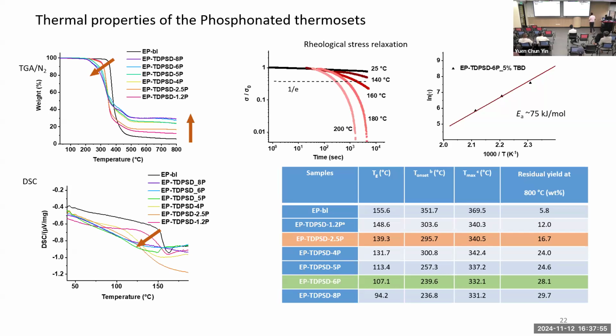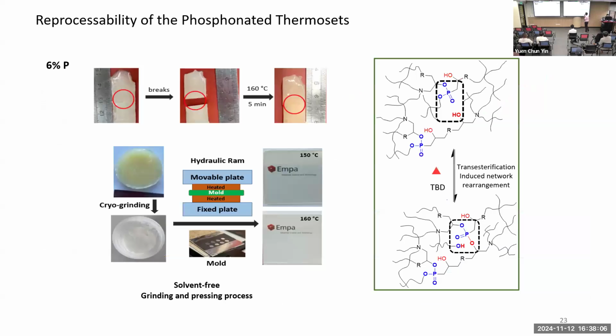Okay. So take home message. Higher the phosphorus, easy to recycle, but also lower is the glass transition temperature, and higher is the char content of the material, I would say. So you can see at 6% phosphorus, you are able to make a material which can be recombined back and forth, broken many times using heat treatment and heal the material.